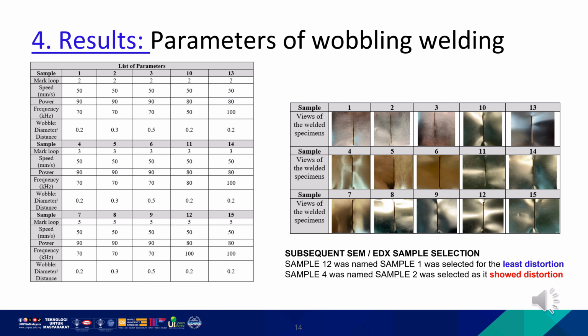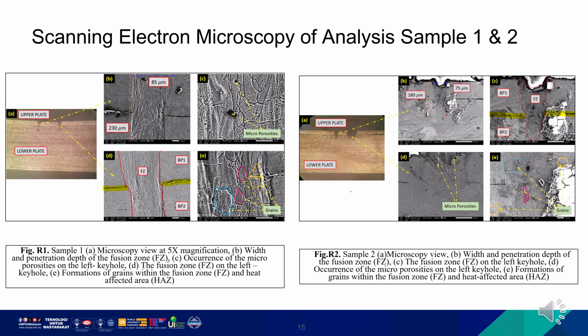Out of these 15 samples, 2 were selected for SEM and EDX analysis. The samples were selected based on least defect and more defect, corresponding to sample number 1 and sample number 2. Sample number 1 was laser welded at 80% power, yielding a high quality weld aspect ratio of 0.37 with minimal porosity, and we can see it revealed uniform grains, clear fusion lines and minor micro voids, which is consistent with strong SS304 joint integrity.